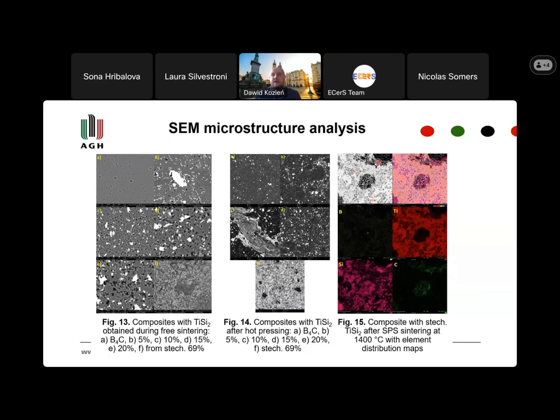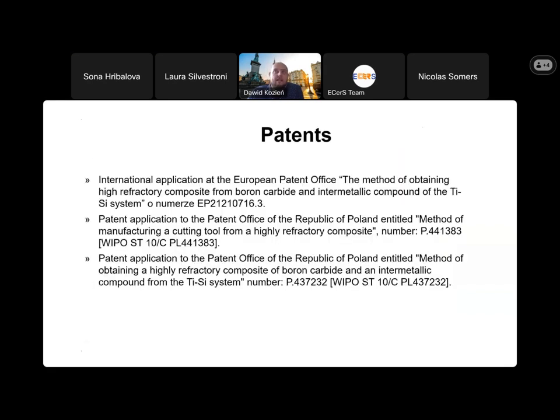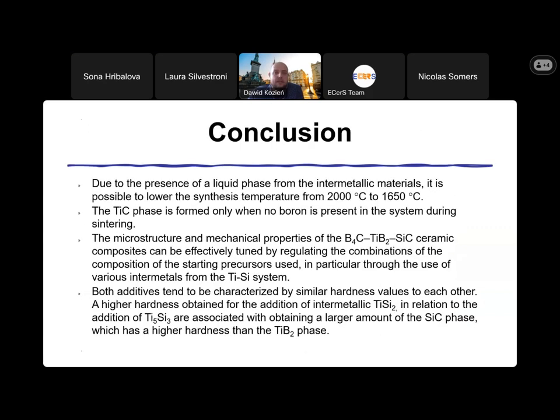That was very fast sintering. So sometimes we have residual intermetallic and different composition in this part. Not very homogeneous like in the HP method, but we have a lot of liquid phase during the sintering, and we have a lot of pores like in typical free sintering, to compare with this SEM that we obtained. And of course, we have some publications of this.